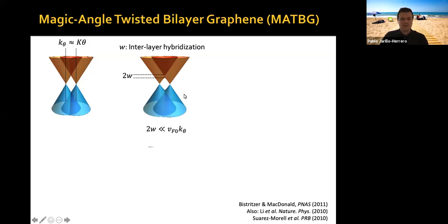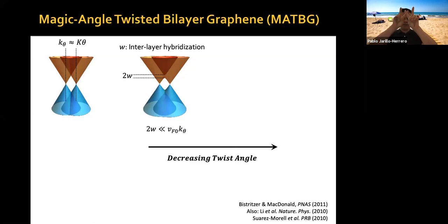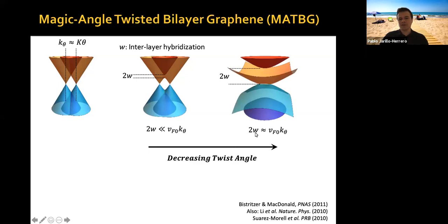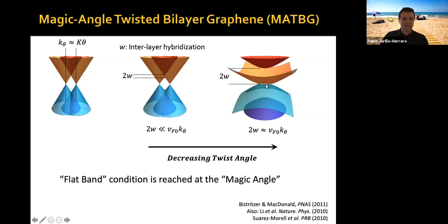However, if you now decrease the twist angle towards smaller and smaller angles, these Dirac cones that touch each other and open a gap here start getting closer and closer, so this crossing point goes towards lower and lower energy, such that at some point this interlayer hybridization becomes of the same order of magnitude as the crossing point here, and then you develop a flat band. Yeah? Now, this flat band condition is reached at the magic angle, a term coined by Bistritzer and MacDonald, okay? And it happens to be about 1.1 degrees, yeah?